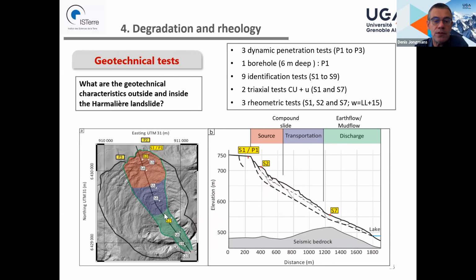We took 9 samples from the escarp to the toe for identification tests, and we performed 2 triaxial tests at S1, behind the escarp, and at S7, which is in the discharge zone, and 3 rheometric tests at the S1, S2, and S7 sites.